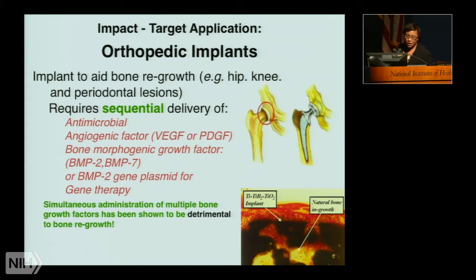And what happens in that case is that the infection rate soars from the primary case to this secondary, this revision case, from lower than 1% to, depending on which review article you might read, 10 to 20%. There's a very real increase in infection. So we have a concern about this. On top of that, we would like to generate a very strong bone interface with the native bone and the implant. The better that interface, the less likely that infection is going to return.